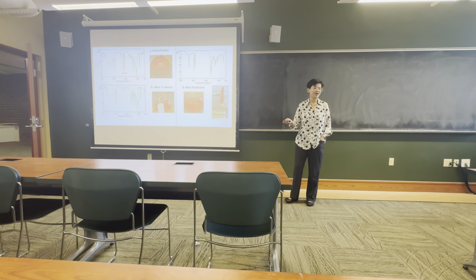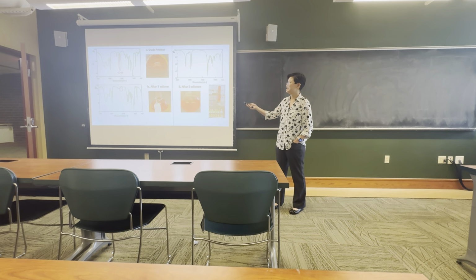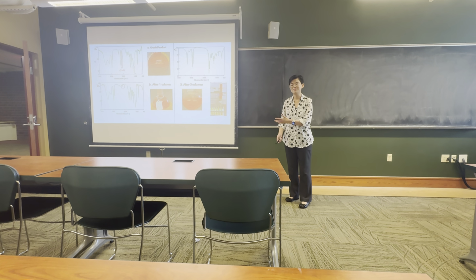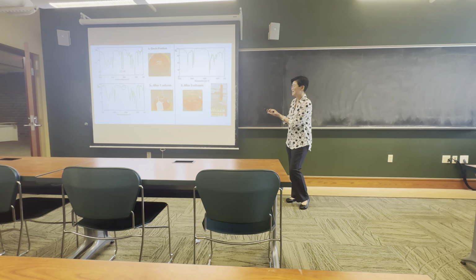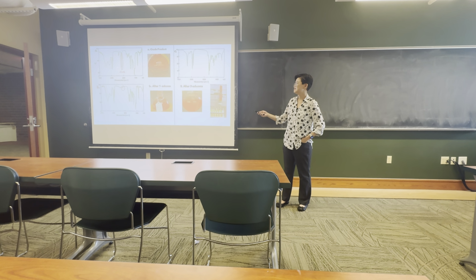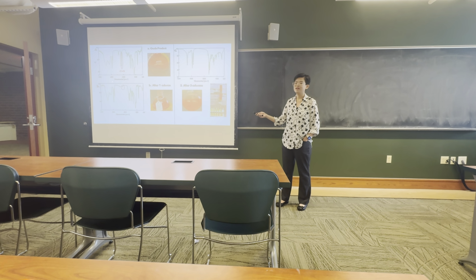Okay, so I'm going to transition back to my zwitterions and the synthesis process. So this was my crude product, and I think that the IR spectra from my crude product are the strongest piece of evidence I have that I synthesized the correct molecule. So this is my crude product, and you can see there's this really prominent peak here around 2000. This is the C=N peak from the DCC.